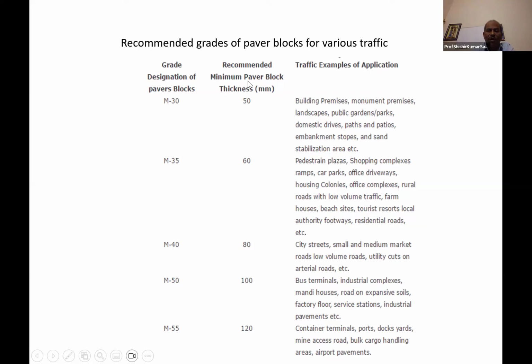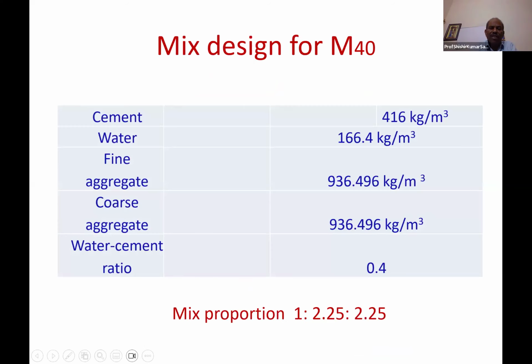And the recommended paver block thickness is 80 mm. Whatever you are seeing on the road, most of them are 50 or 60, M30 or 35. It is used for building premises, monumental premises, landscapes, public gardens, domestic drives. So usually it cannot be used as a pavement, but you can move around, or 60 can be used for car parking. And the mix design considered is 1:2.25 to 2.25. Water cement ratio 0.4.